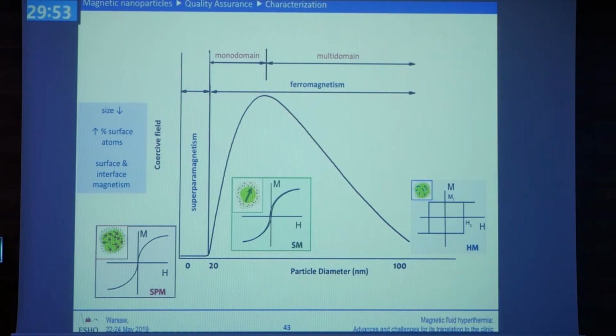Okay? So what we know is that as the nanoparticle becomes larger and larger, the magnetic dipoles, the small compasses you have here, can behave differently from each other. When the nanoparticle is very small, they behave independently. Then as the particle diameter increases, this is the ferromagnetic area, you have one single magnetic dipole, so all of them are in the same direction, on the same page. And when you have a nanoparticle that becomes even larger, then inside the nanoparticle you can have magnetic walls and different domains where the small magnets are oriented in different directions together.